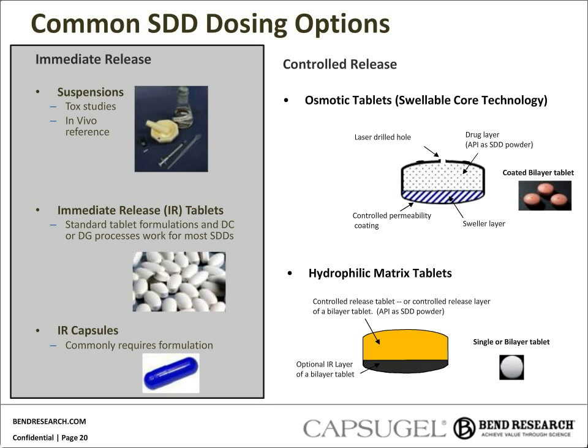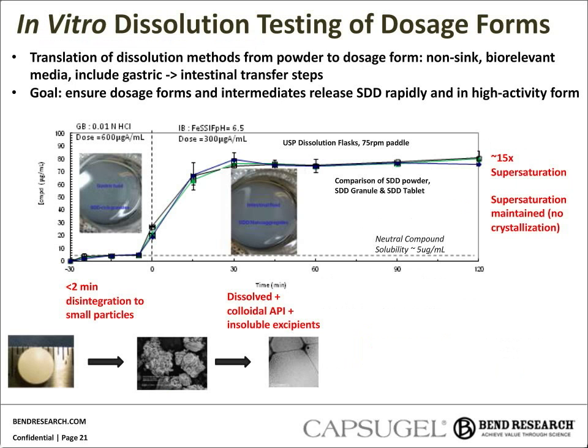Dosage form is a key piece of all performance, manufacturing, and stability. Dispersions can be used in a wide variety of dosage forms. This slide is monolithic based, but we also use multiparticulates with dispersions regularly, both for IR or modified release. The usual goal for an IR SDD dosage form is to do no harm, essentially. We want to understand that we're releasing a high energy dosage form as we expected from our powder testing. This just shows one example where we've created a tablet that disintegrates rapidly back to the primary particles using the same tenets of gastric to intestinal transfer and testing powder versus tablet to show that we get the same supersaturation, the same rates, and no precipitation.